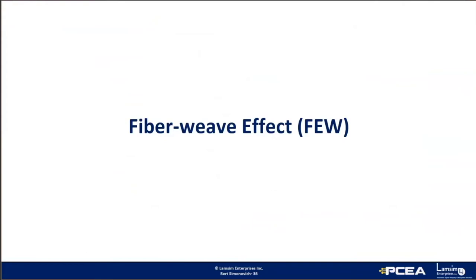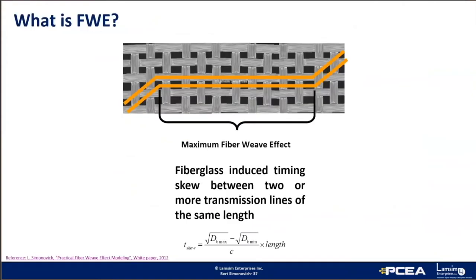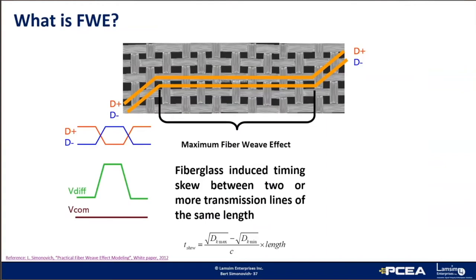All right, next I'll touch a bit on fiber weave effect, sometimes referred to as glass weave skew. So what is fiber weave effect anyways? Well, it's when there's a timing skew between two or more transmission lines of the same length caused by the glass weave. If we start with two complementary signals, D plus and D minus, with no skew, the differential signal is not distorted and there is no common signal.